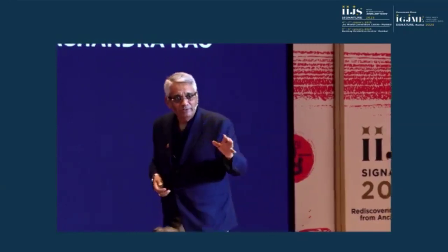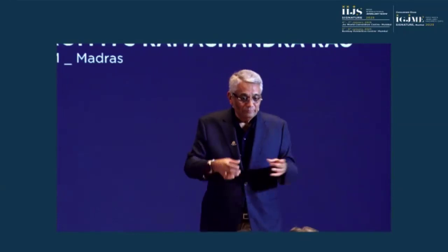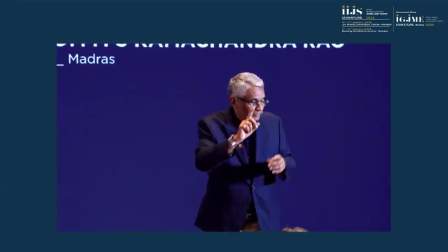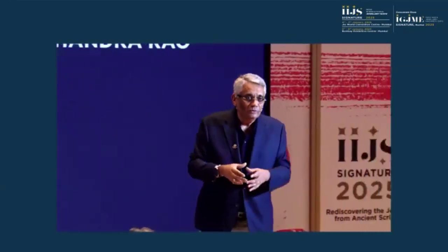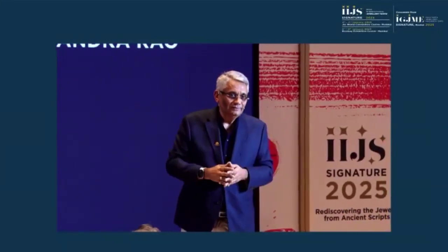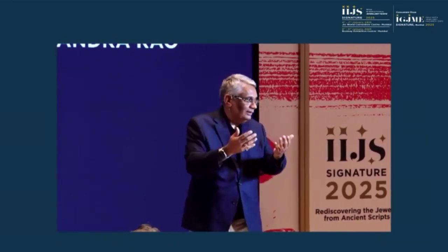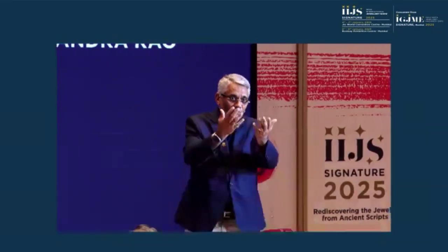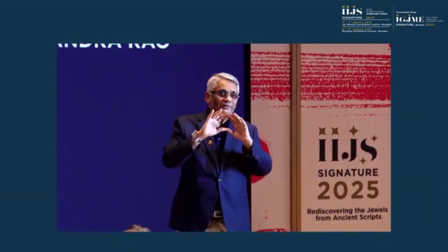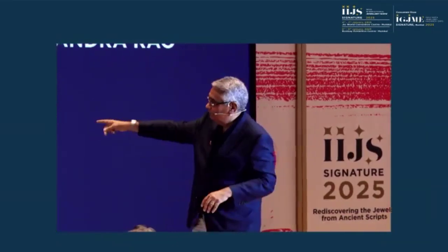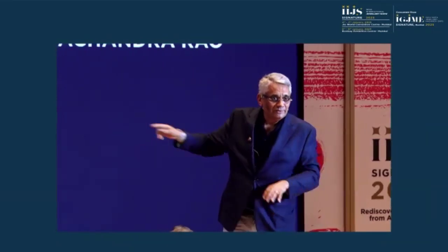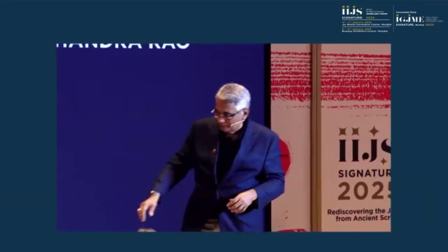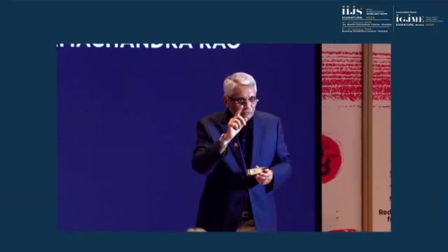I think Europeans are doing it, and Russians are also masters in growing big crystals of diamond in HPHT. The advantage of HPHT growth is that the diamond that grows in HPHT comes with natural facets. Not as many as a normal diamond would have, but crystallographically it grows along those facets. But the one that you grow with the CVD process is like a thin slab, like this one. Then you make the facets. So there is a difference.